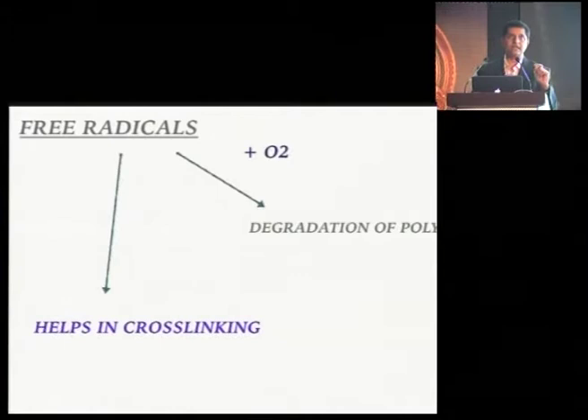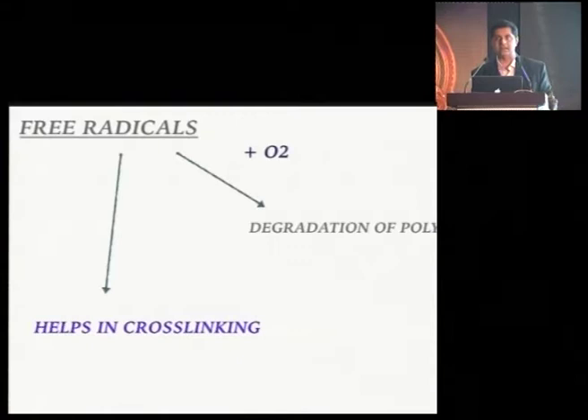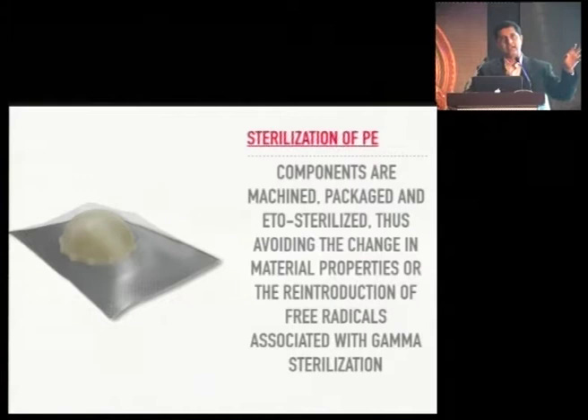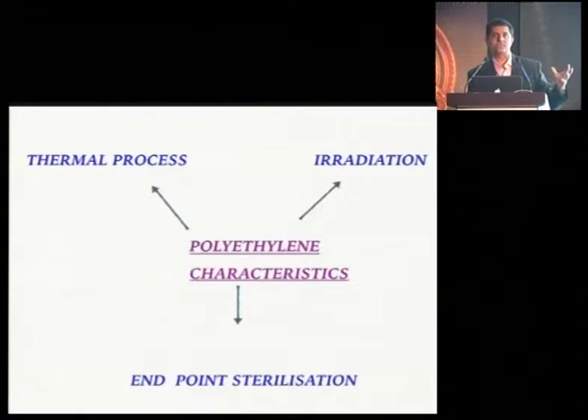That degradation is why many surgeons insist on not opening the poly until the time of insertion. Sterilisation is also very important. Many companies now use ETO sterilisation. Previously gamma sterilisation was used, but gamma sterilisation again causes degradation of the poly. So polyethylene characteristics from each process — whether thermal processing, irradiation, or end-point sterilisation — carries ways of degradation.